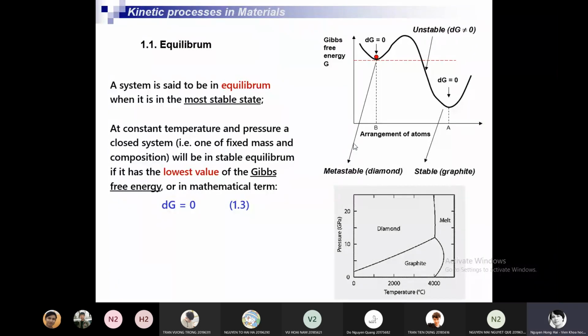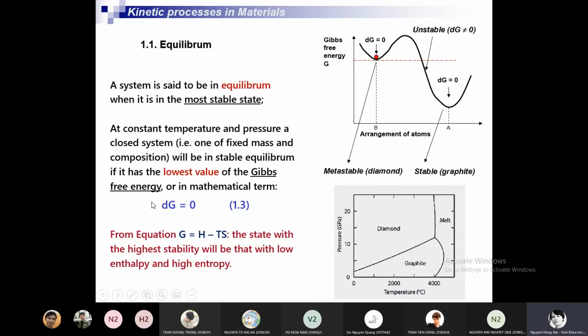From this equation we can conclude that the state with the highest stability will be that with low enthalpy and high entropy. Low enthalpy and high entropy, so free energy will be low. And if this free energy has the lowest value, we have a stable system. So the state with higher stability has low enthalpy and high entropy. If the state has high enthalpy and low entropy, we have an unstable state.